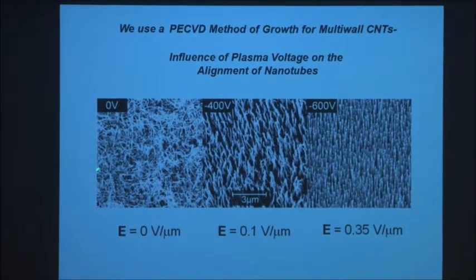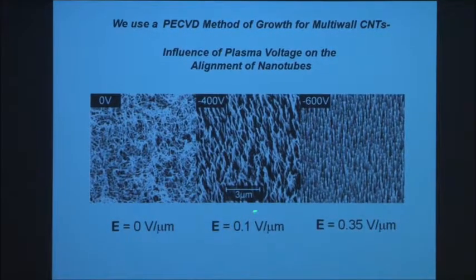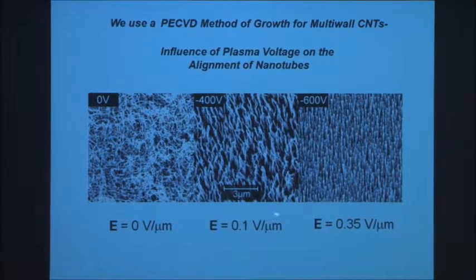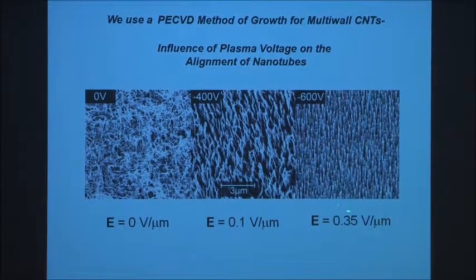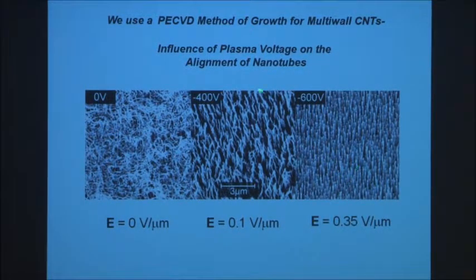If you use CVD without a plasma, you can also grow them. But in that case, what you get is something like spaghetti, because there's no way to try and get the tubes to line up. There's no field. You end up with spaghetti. If you apply a small field, then you get a little bit of lining up. Above about 0.2 volts per micron, we found you get the tubes lined up. So the influence of plasma voltage on the alignment of the nanotubes. So we've got one way now to control the direction of growth of the carbon nanotubes.